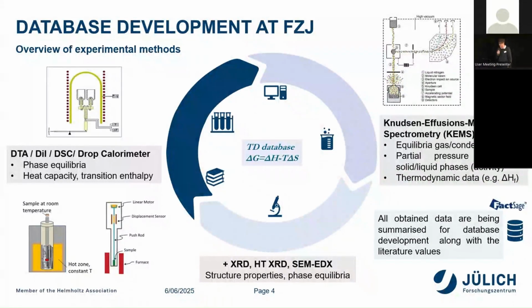We can also measure activity and formation enthalpies using a Knudsen effusion mass spectrometer, which is also quite special. In addition to the thermodynamic data, we can also generate crystallographic and structural property data using XRD, high temperature XRD, and SEM EDX.